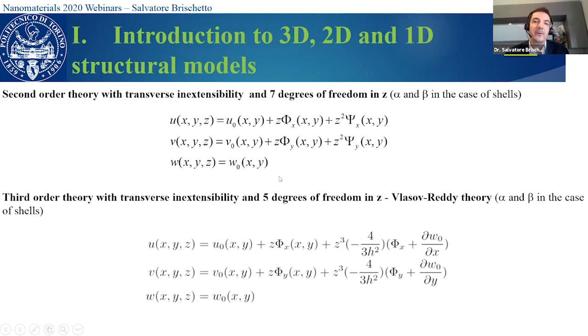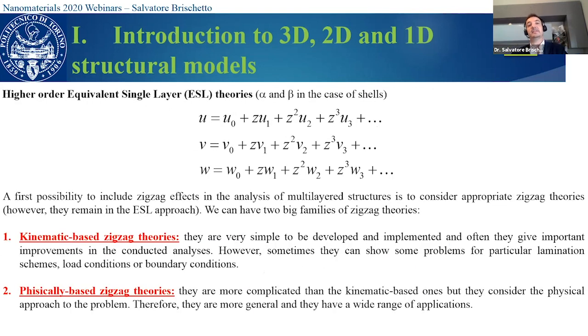Obviously, all these theories have constant transverse normal displacement. And this is a problem because in this way, we discard the transverse normal strain, okay? And for some problems, for example, very thick plates, this is a great approximation. Moreover, these models have some problems, for example, the Poisson locking problem. We solve this problem by means of the use of reduced elastic coefficients and so on. Then there is another family of higher order theories. Professor Dimitri spoke about this.